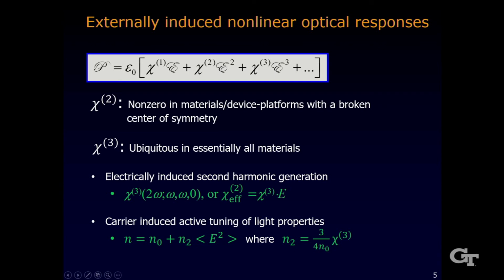Here you see, I believe, the very first equation in any nonlinear optics textbook, which shows the induced polarization field in the material as a function of the electric field component of the optical wave. The first term is really nothing, not nothing. It's the first-order component, which is typical. Basically, it just gives rise to the regular refractive index. You see, it's the square root of 1 plus chi 1 that is the refractive index of the material.